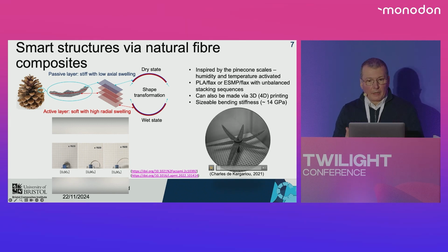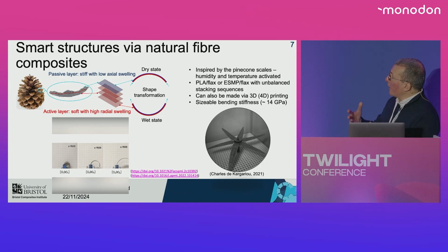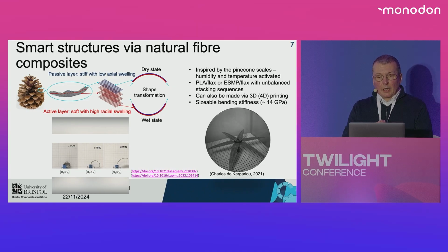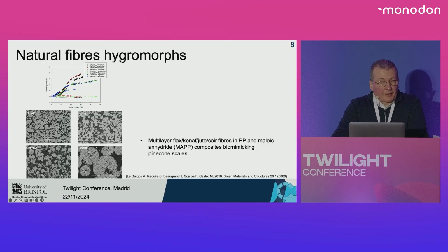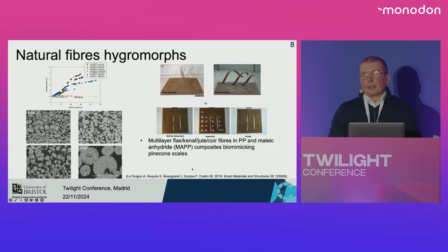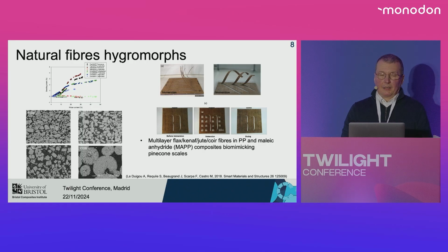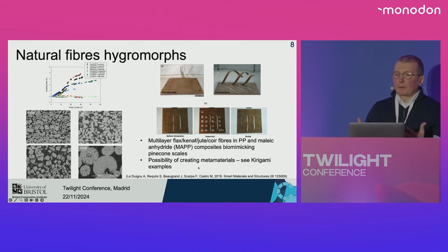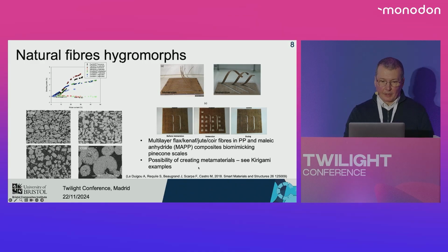And just to show you, when we use 3D printing, 4D printing characteristics, the type of really complex structures, this is a calla lily that forms when the relative humidity is changed from 20% to 50%. Flax is not the only fiber, or natural fiber, that can be used for these types of actuators. You can also use kenaf, jute, coir fibers. The matrix can be a thermoplastic, polypropylene, or maleic anhydride, not only the thermoset that we have seen before. Quite interesting, you can really make this type of hygromorph composites and then apply every type of technique from kirigami, architecting, to obtain these types of metamaterials, which are bio-based in this case.